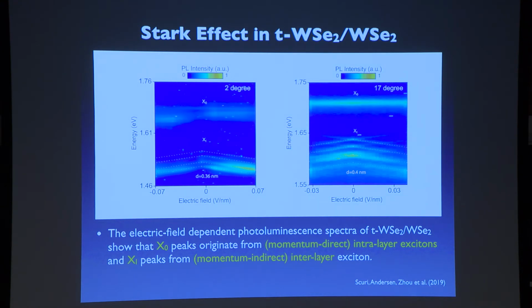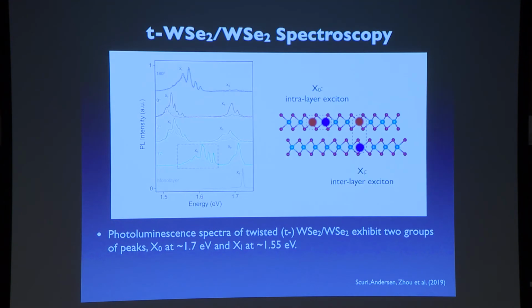What does it tell you? This tells you that these peaks, at least the species that are responsible for these peaks, do not have an electric dipole moment perpendicular to the electric field. These ones do. That's what it shows. From this picture, you can tell this one should not shift as a function of vertical electric field. This one should. So we can assign this one to the intra-layer exciton, and this one to the inter-layer exciton.